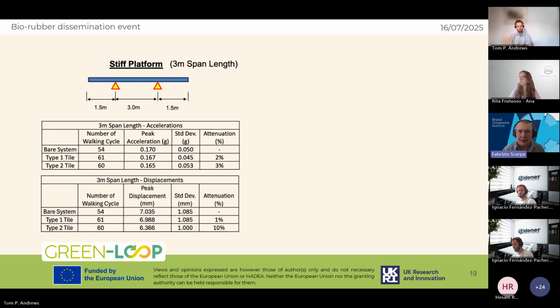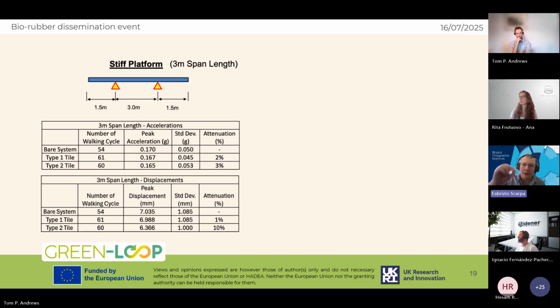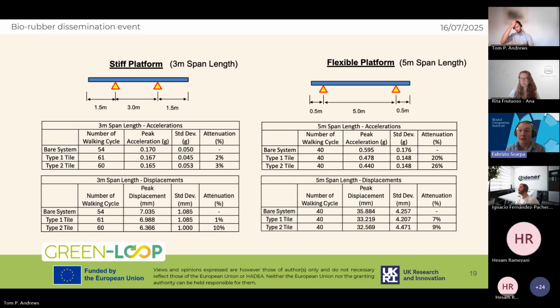If you look at the stiff platform, there is already a tangible effect when we consider the presence of the panels and also the presence of the rubber with the lignin. You can see that there is an attenuation of the peak acceleration. Also in terms of displacement, you have an attenuation. More interesting results appear when we consider a flexible platform this time around. And Tom, if you can click over once again.